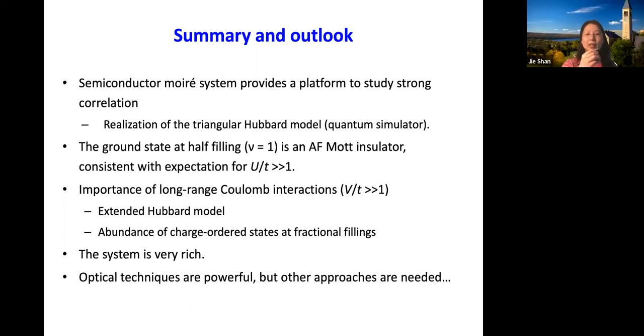Well, this is somewhat lucky in terms of arrangement. The sensor layer is also WSe2, and the system we look at is WSe2 and WS2. Because of the Moire potential, the WSe2 in the sample layer has a smaller gap, and the WSe2 in the sensor has a larger gap. So when you gate the moiré system, the charge goes into your moiré, and it leaves the sensor layer charge neutral. But you can come up with gates to control doping density in the sensor layer as well. I don't see why this cannot be done if you need to. Okay, thank you.